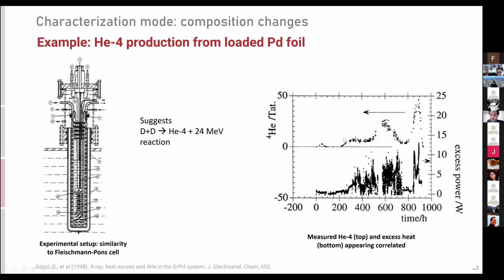And then they also measured helium. This was a closed system where they keep all the gas that was accumulating, and they found that the amount of helium that they picked up correlated to the amount of heat that was produced in that system.